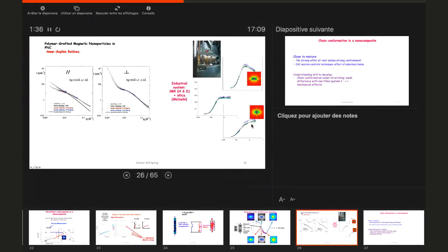This curve is abated by the deformation. But you see that in both cases, the signal of the dark and the green symbols, which correspond to the system with and without fillers, are the same. There is a slight difference with the blue system, which corresponds to a larger concentration. But this difference is more or less the same for the isotropic state, the deformed state, and so on.